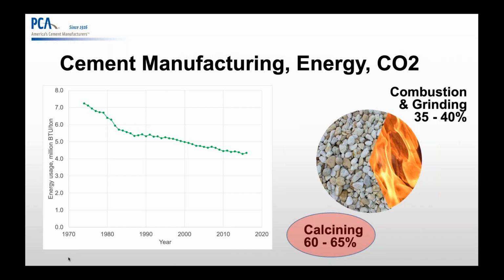Since the 1970s, improvements to US cement manufacturing have resulted in more than a 40% decrease in production energy. CO2 from cement manufacturing has two components: combustion/grinding, which is using natural gas and coal to heat a kiln to 2,700 degrees Fahrenheit, and electrical power to turn a finish mill. This heat is used for the second component, calcining, which is breaking down chemical bonds of limestone, calcium carbonate, into lime, calcium oxide, and carbon dioxide. Lime is a key ingredient in cement manufacturing.